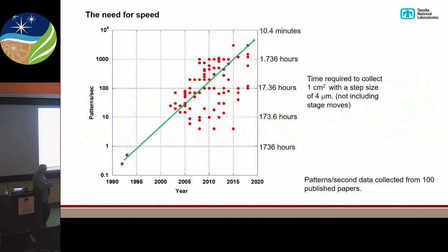And the reason that's important is look at this scale here. So this is the time required to collect a 1 centimeter squared image with a step size of 4 microns, not including the stage moves, because that takes a second per stage move roughly. But if you look here, back in the old days, that would be 1,700 hours, totally undoable. But now when we're up around 3,000 patterns, you're talking a couple hours to cover a centimeter squared. So that's really a remarkable improvement. And as we get faster, I think we're going to be up where this sort of thing takes no time at all to get done.